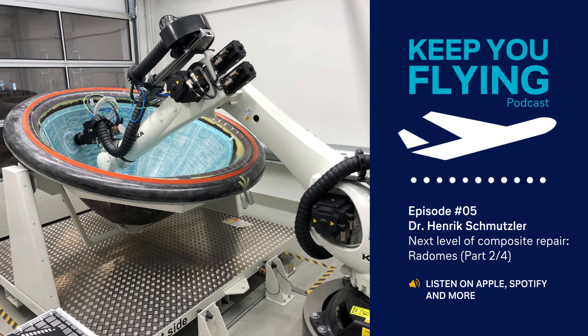The greatest challenge in implementing our ARC robot for radome repairs was to still enable a load transfer from the remaining skin to the repair laminate. Radome skins are fairly thin — less than 1 mm — as they are designed to be highly permeable to radar waves. Scarfing these glass fiber-reinforced plastic skins with a ratio of approximately 1 to 70 leads to immensely high accuracy requirements. With our adaptive scanning and milling process, we have already proven accuracies in the range of ±0.06 mm, which is incredibly close to the general maximum achievable with an industrial robot of this size and accuracy class. Overcoming these challenges and finally reaching the required accuracy called for a long and painstaking iterative process.